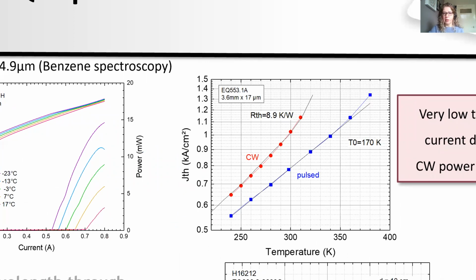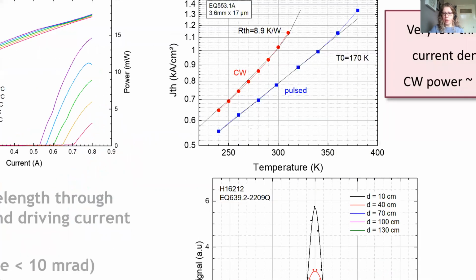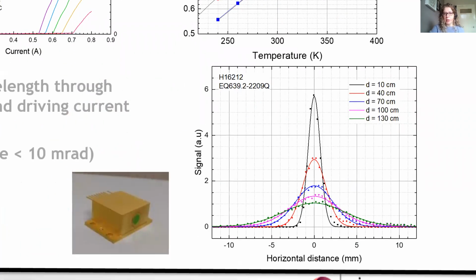You can also see in this bottom graph here the beam profile as a function of distance. So typically we see a full width at half maximum of the beam of 4 millimeters at the output of the package. But then if we move to about 1 meter from the package, you can see that the full width at half maximum increases to about 8 millimeters.